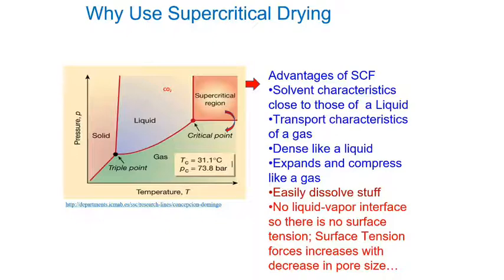Meaning, as a gas, you know a gas is going to blow things very fast. So the transport of a gas is much faster. As a liquid, it can dissolve stuff really well. So when you have a fluid that has that good combination, you can use it, in this case, to dissolve the solvent and then take the solvent out. We use CO2, and CO2 has a critical point of around 31 degrees and 73 or 74 bars. So whenever we are here, now we can use it. Why are we using supercritical fluid? Again, because we want to overcome what we call the surface tension.